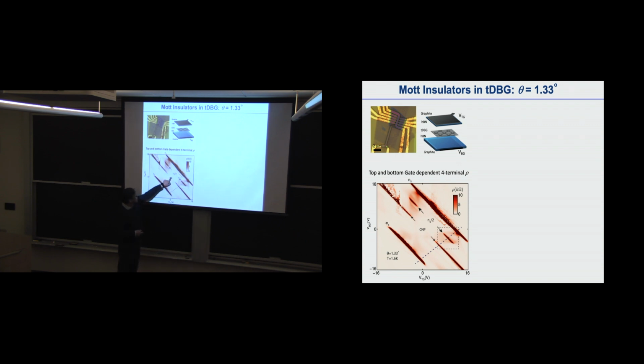This is charge neutrality, the center of the gap, and this is the part where we expect the so-called single particle gap to open up, at the corner on the left. Usually the correlated state appears somewhere at half filling or in between. What you see here is that there's nothing there, but on this side, when I apply some displacement field, electric field, I start to see this dark red region, which is an insulating region that appears here.